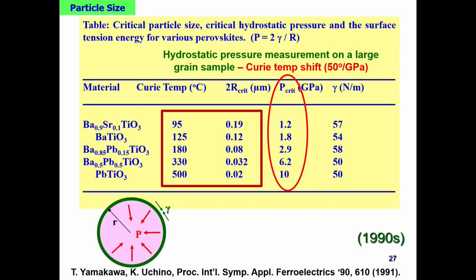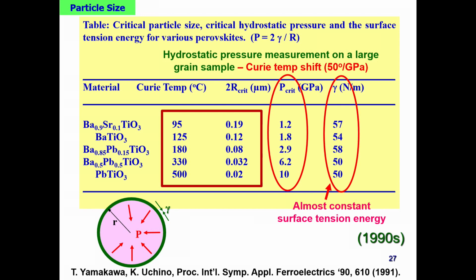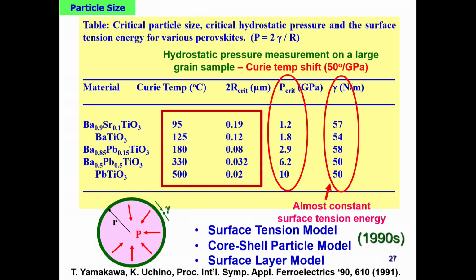So we speculated about the hydrostatic pressures. In our paper here, we mentioned a surface tension-like model. But you don't need to keep a real surface tension. A core-shell particle model or surface layer, doesn't matter. At least you can calculate how large a hydrostatic pressure is created inside, okay? Anyhow, this is almost a constant value. So why is this constant really constant? We need to wait for some physicist's explanation. So compressive pressure is higher for the smaller particle size. This seems to be really true.